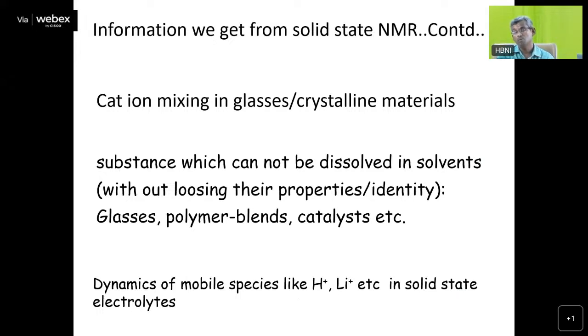Similarly for polymers and blends, carbon-13 NMR. People do carbon-13 NMR extensively to understand how different structural units or different backbones are linked, the chain linkages in polymers. Also in the case of polymers, as a function of temperature, the polymer groups present undergo softening, and accordingly movements happen with these polymer molecules present in the system, and this also can be monitored with the help of carbon-13 NMR.